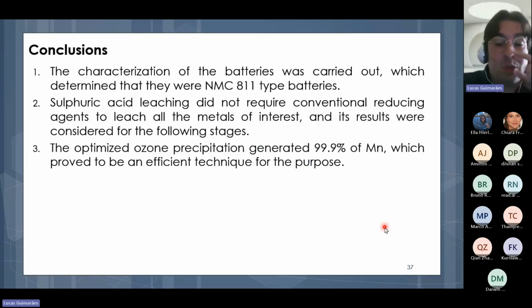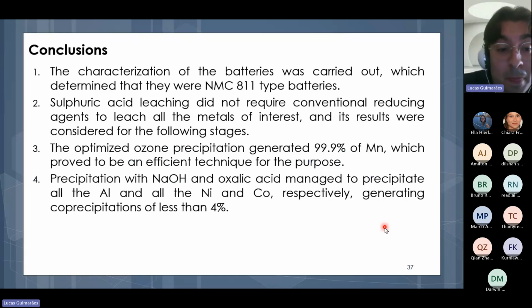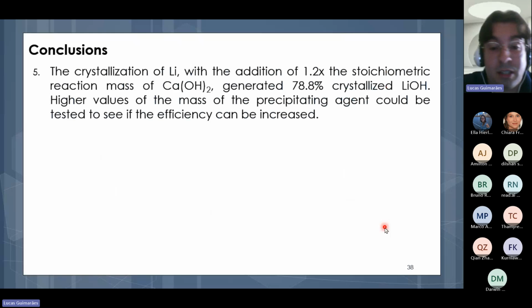The optimized ozone precipitation generated around 99.9% of manganese, which proved to be an efficient technique for the purpose. The precipitation with sodium hydroxide and oxalic acid managed to precipitate all the aluminum and all the nickel and cobalt respectively, generating co-precipitations of less than 4%.